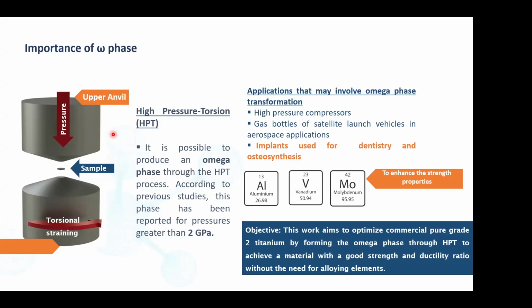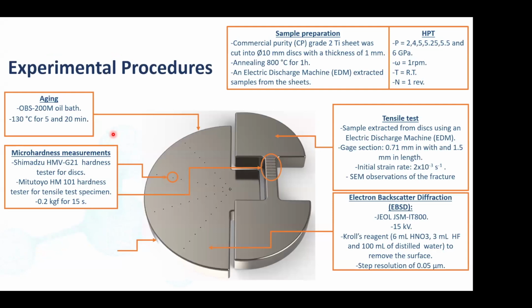So we have been working with commercial purity titanium for some time now, and I'm going to show you some results. So very traditionally, what we do, and this is probably going to repeat itself for other alloy systems that I will show, is that after we process by HPT, we can grind, polish and etch the sample to reveal the microstructure by optical or electron microscopy. We can take hardness indentations, and as I said before, the strain will depend on the radius of the sample, also the number of turns. So measuring a few radii from the center to the edge will give us a nice distribution of how the